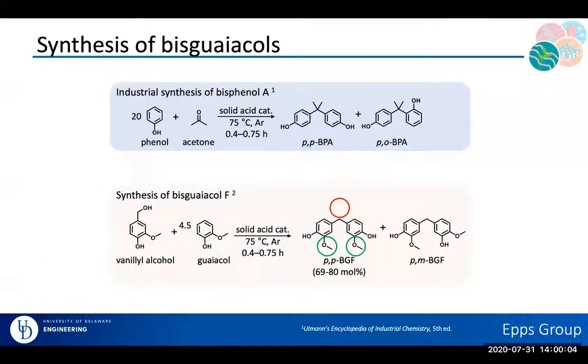So in our particular case, we said, can we use some of the same feedstocks that we talked about previously? Just as one example of how we thought about doing that, at the top, I'm showing one of the industrial synthesis routes to BPA. At the bottom, I'm showing our molecule, BGF, bisguaiacol F. This molecule can be made from vanillyl alcohol and guaiacol, two of the products from the lignin depolymerization process. The thing I want to point out is that we're going to use the same solid acid catalyst, same temperature, same environment, and same time, so that these materials really become much like a drop-in replacement to BPA in terms of designing, for example, a polycarbonate.